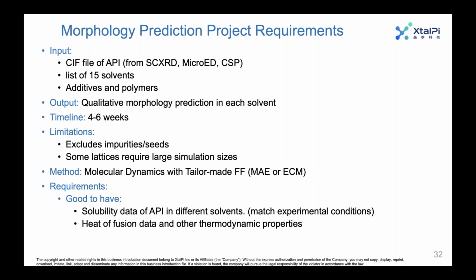The method, again, is molecular dynamics with a tailor-made force field, and we'll use most likely the modified attachment energy model. But if you have some data that suggests that maybe the system is highly sensitive to a variable like temperature or supersaturation, we could explore using the Einstein crystal method for that type of project.